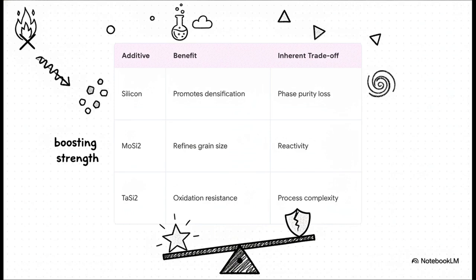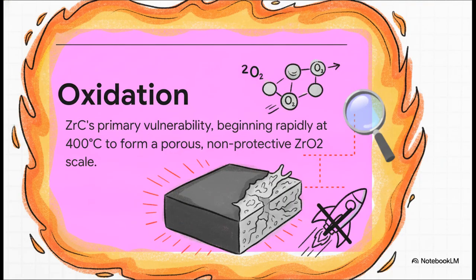You might risk compromising the phase purity of the material, or you could accidentally make it more reactive to its surrounding environment. Which brings us to ZrC's Achilles heel: oxidation. Despite its absolutely incredible heat resistance, when it's exposed to oxygen at temperatures as low as 400 degrees Celsius, it starts to oxidize rapidly. It turns into this porous, flaky scale of zirconium dioxide that just falls away, offering zero protection to the fresh material underneath. For an aerospace vehicle flying through Earth's atmosphere, this is a literal showstopper.